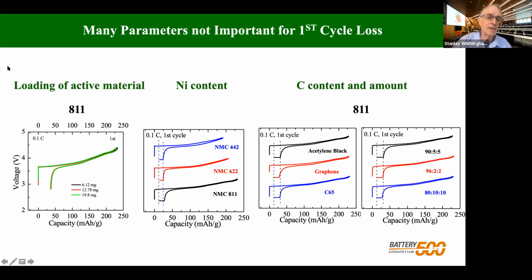So my students looked at a whole lot of different parameters, and these are basically parameters that we found were not important. And this was somewhat of a surprise. So the loading of the active material was not important. So this is going from 6 milligrams to 20 milligrams, exactly the same. Even more surprising, the actual nickel content had no effect. So with the lowest nickel content, you get less capacity. So you see with 80%, you get more capacity. That's one of the reasons for going here. But you can see in the end, you don't gain anything. But I should point out here, you're seeing now this little step here.